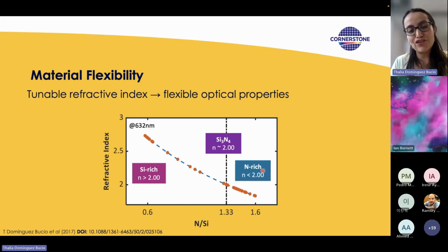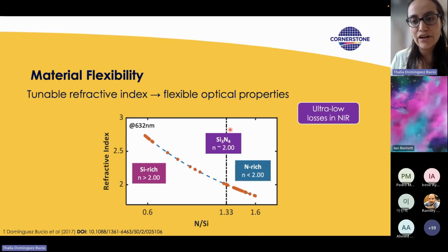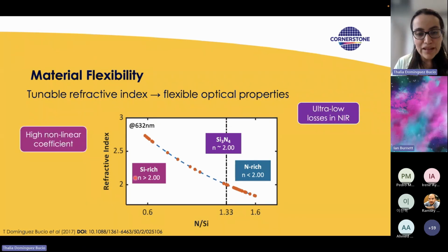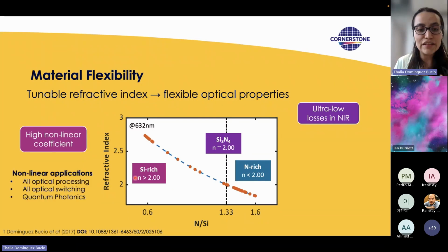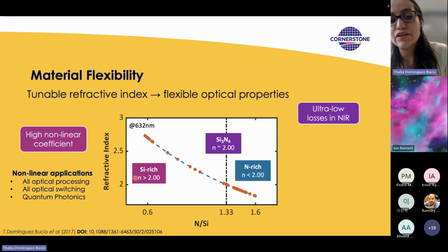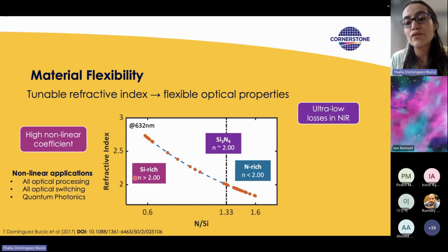Now, why is this important? Because each of these layers will have different optical properties. So if we talk about the stoichiometric silicon nitride, it tends to have very low losses in the near infrared. So typically when we talk about foundry services, this is the kind of silicon nitride that you use. It's the stoichiometric silicon nitride, which is deposited at high temperatures, that has very low losses for the near infrared part of the spectrum. If you go to the other end, in the silicon-rich regime, the advantage is that because you're increasing the silicon content, you will have a high nonlinear coefficient, which makes this material very suitable for nonlinear applications such as all optical processing, all optical switching, and even some nonlinear processes requiring quantum photonics.